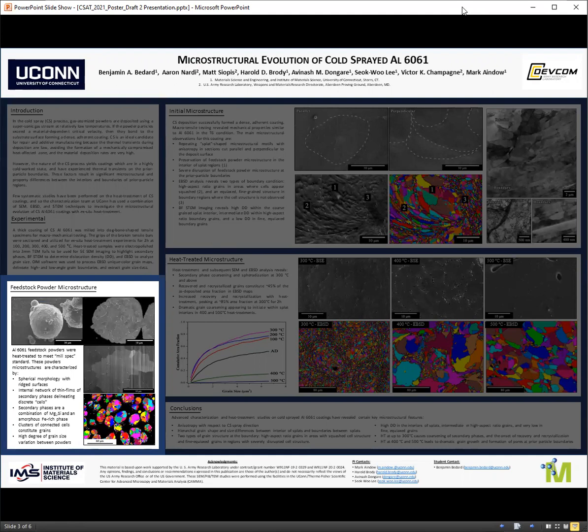These powders are characterized by a spherical morphology with ridged surfaces, an interior network of thin film magnesium and iron-bearing secondary phases which delineate discrete cells. Clusters of these cells constitute a single grain, as seen through channeling contrast in BSE imaging and EBSD grain mapping.